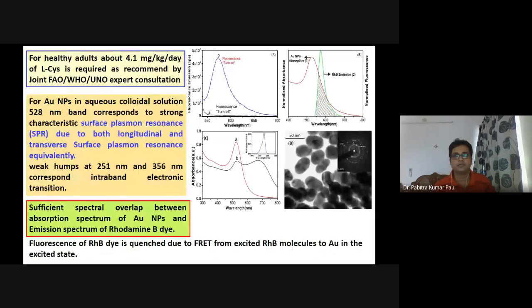You can see the structure of the gold nanoparticles, and the fluorescence of the dye molecules is quenched after addition of the gold nanoparticles to the dye solution. You can see this picture, this one.